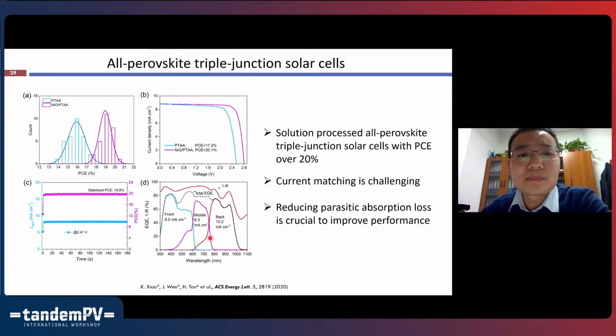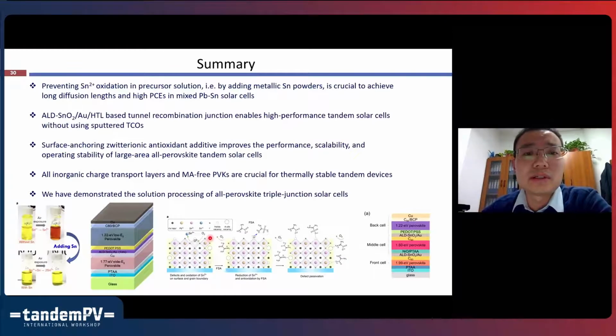So here I just give a short summary of my talk today. The first take-home message is that it is important to prevent tin oxidation in the precursor solution. What we can do is add some metallic tin powder in the solution. In this way, we can achieve longer diffusion lengths and also higher efficiency in the perovskite solar cells.